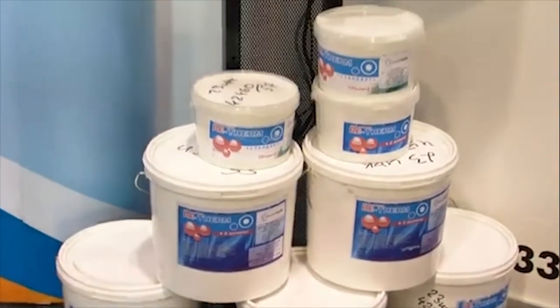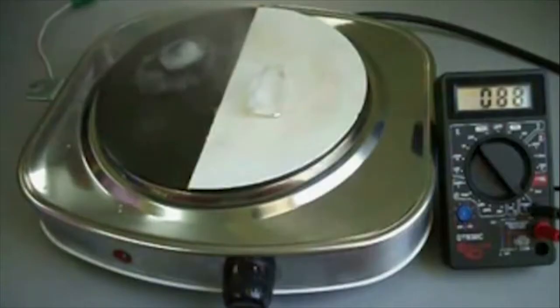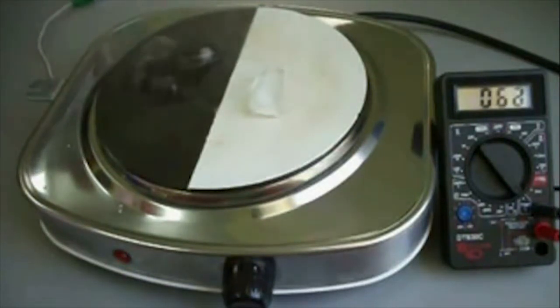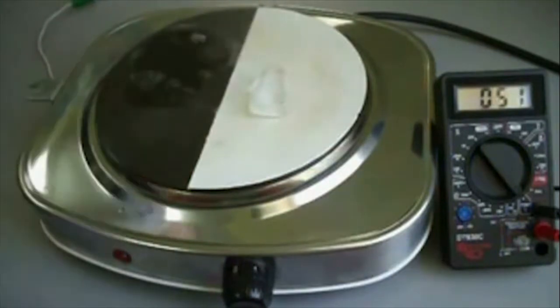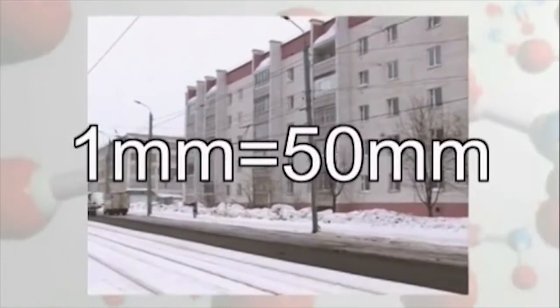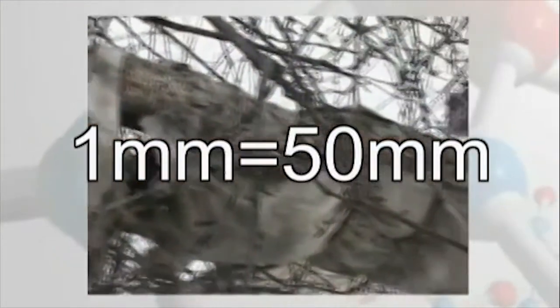The test shows that the heat transfer from 1 mm thick RE-THERM is lower than that from 50 mm thick conventional insulants. It indicates that precious heat is not emitted into the environment but fulfills its functions. 1 mm of RE-THERM equals 5 cm of conventional insulants.